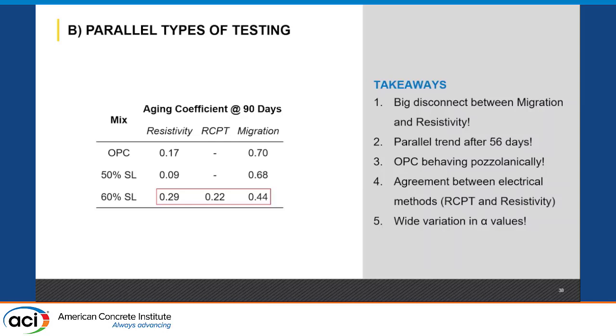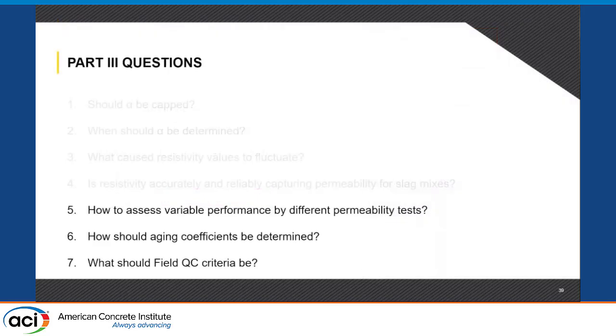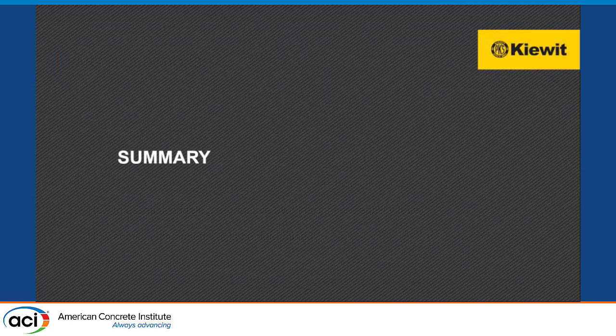And this is a very real question that we're facing. You have 3 tests measuring the same property, giving you 3 different answers in different directions. This 0.29 is sort of close to this 0.22, so I'd say they're close to each other, but they're low. Migration is more in line with what I would expect, so I like that number better. But again, you see even OPC can be in the 0.7 range. So part 3 questions are, how do you assess variable performance with different tests? How should aging coefficients be determined, and what should the QC criteria be?